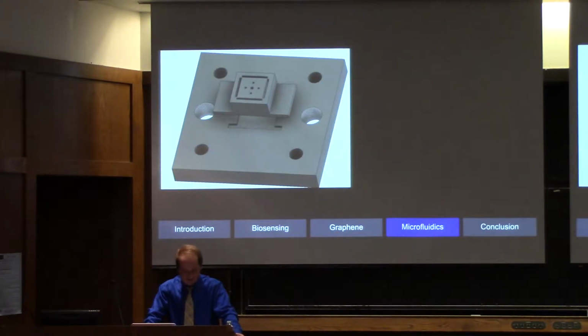So our lab solution to this was the device that you see here on the left. I actually drew this on an AutoCAD program, and we had it made in the machine shop in the basement of Higgins. It consists basically of a base for holding the biosensing device. That's the big square that you see on the bottom. And this has 4 holes in the corner to allow it to screw into a transfer stage that could greatly increase the stability of these tests.